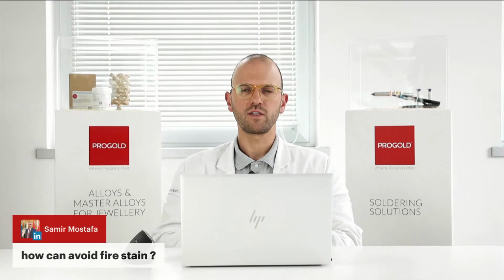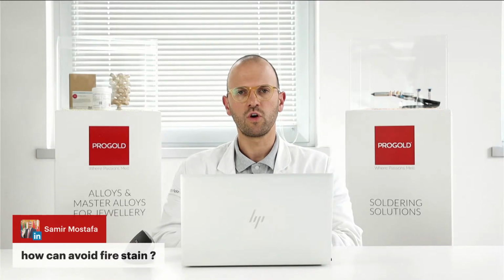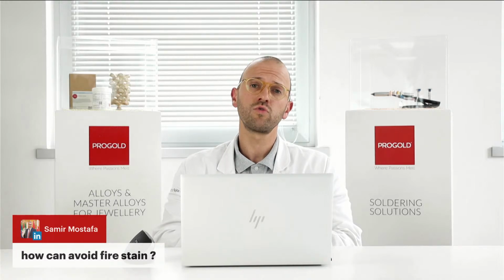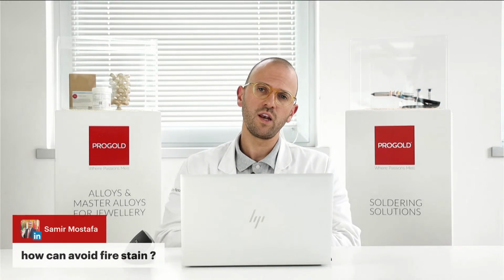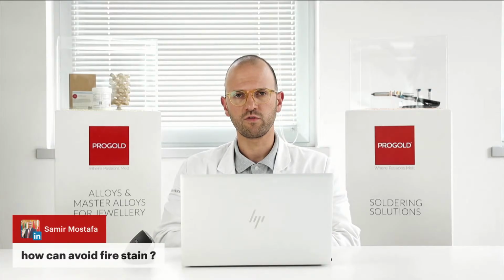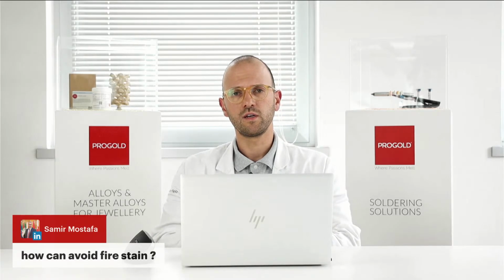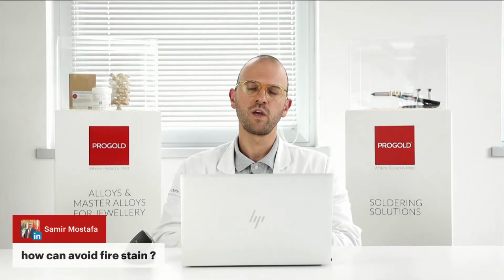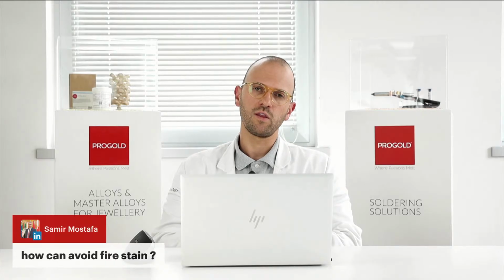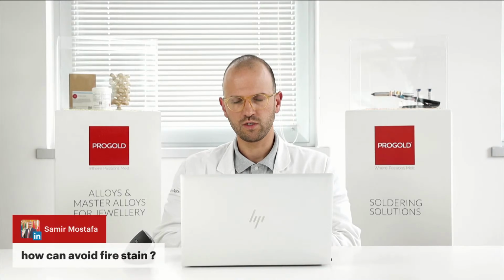How can we avoid firestain? As I explained, firestain can be avoided by working on the temperature and on the protection of the metal from oxidation during the solidification. So leaving the flask inside the casting furnace during the cooling could help prevent contact of the hot metal with the oxygen, and also cutting the time between casting and flask quenching.